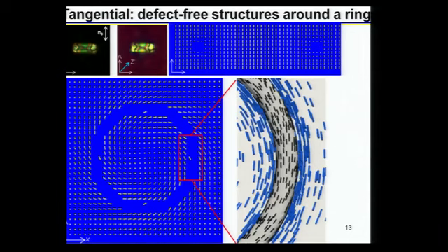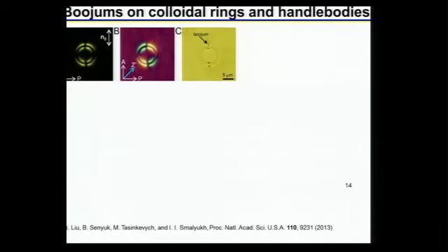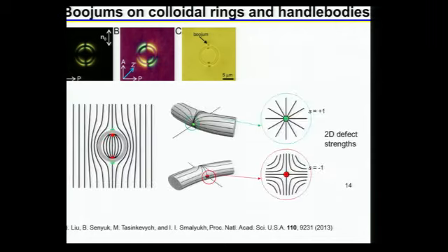also observe boojums. And so it's the same type of ring, right, which we can simply introduce into a nematic liquid crystal with planar alignment. And then you can see we can observe 4 different boojums in here that are clearly seen from this optical microscopy texture because of scattering from the boojums themselves, right? Now we can reconstruct director field structure that is depicted in here, and what we see is that there are boojums of different charge, right?